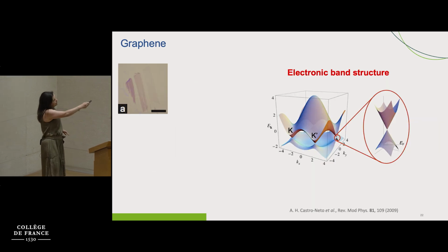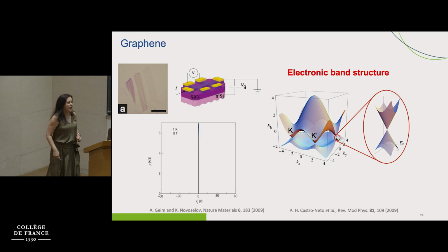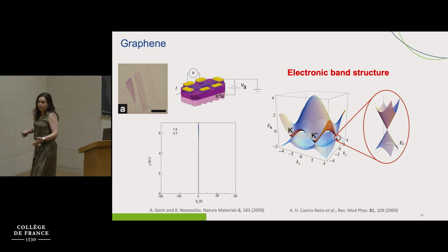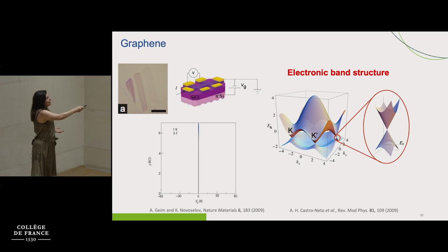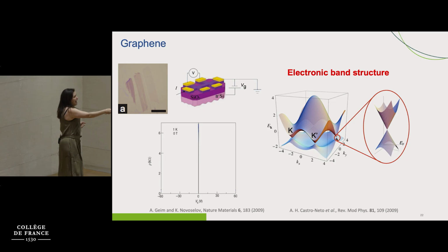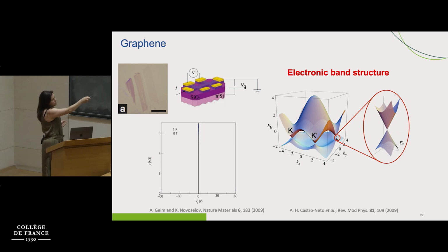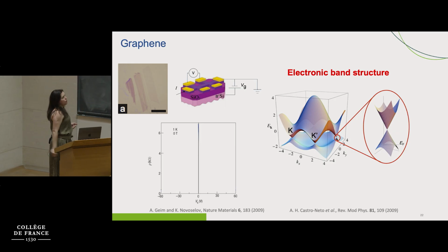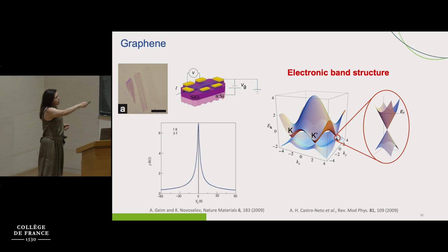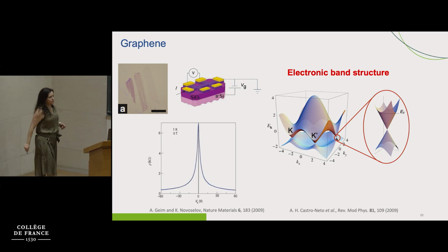So now, from a more experimental point of view, if we take a layer of graphene, which, as you know, has a linear energy dispersion, and we make a device out of it, and we're going to measure transport. Okay, we are going to pass the current from this side of the device to the other side, and we're going to measure the voltage drop. As we change the Fermi energy through this gate electrode, what we are going to see is a strong increase in the resistance and then a decrease.